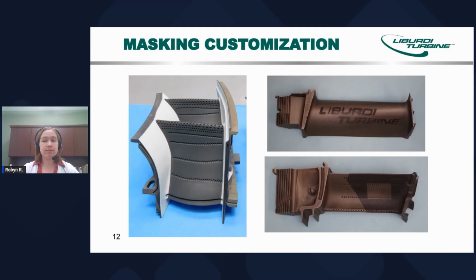Additionally, that separation of deposition from diffusion allows us to go back and clean off areas that are difficult or near impossible to mask before or during the deposition, once again allowing us a higher level of precision. Overall, it can allow us to take on more specialized jobs as required. For example, recently we had a set in-house that had a small area around a platform that experienced rub damage. We were able to take those parts, recoat the area without the need for a full repair and without affecting the rest of the part.